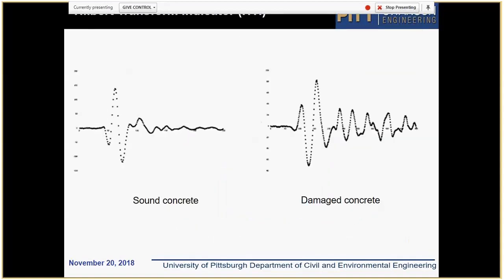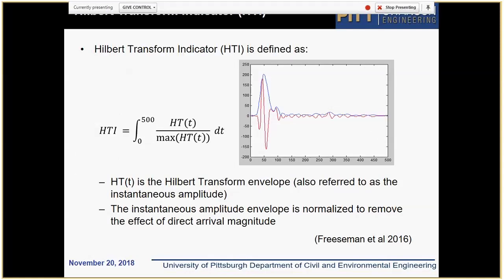We also tried to evaluate damage within concrete, and we used the technique we developed previously for old concrete, and we use it here. So in this case, we take an envelope of the signal and make certain transformation and calculate an area under the curve.